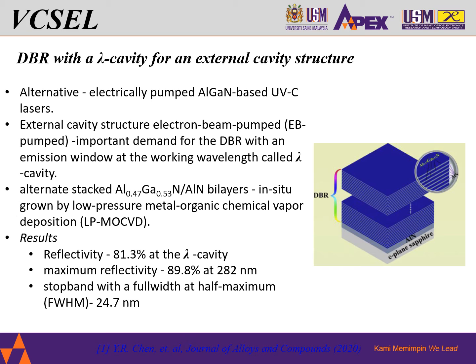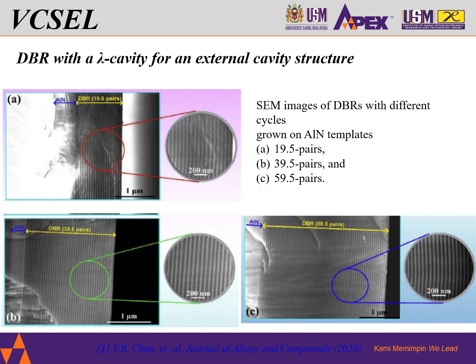Through this method, the reflectivity was increased to around 81.3% at the lambda cavity. The maximum reflectivity achieved was 89.8% at a wavelength of 282 nanometers. This also results in a stop band with a full width at half maximum, FWHM, of 24.7 nanometers. These are images of DBRs with different cycles grown on aluminum nitride templates. The first one has 19.5 pairs, the second one has 39.5 pairs, and the final one is 59.5 pairs.